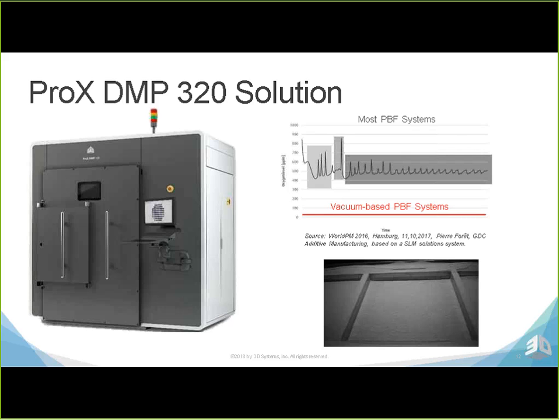With a vacuum powder bed system, obviously that removes that as an issue. So I think really what we focus on for the DMP 320 is to use a vacuum system to remove the oxygen initially, allowing us to operate under 25 parts per million. What this does, and everybody will tell you, yes, our powder's recyclable. The majority of the industry, when they say they recycle powder, what they mean is they can remove larger particles and then get back to a particle distribution that can operate in the system. What they don't mean is that their powder is chemically the same or has not chemically changed.